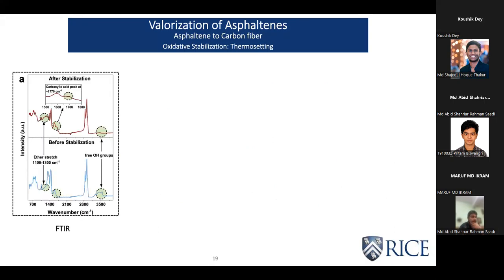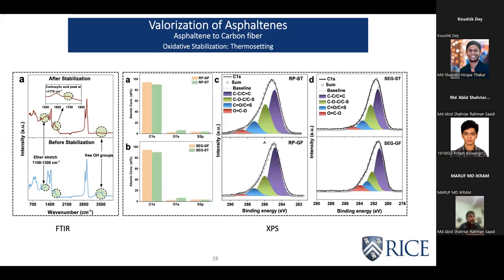We tried different types of stabilization routes, and the one that worked was the multi-step stabilization. We used FTIR, Fourier transform infrared spectroscopy, to confirm that the fibers had been oxidized. Here, before stabilization, and after stabilization, we saw this ether stretch. Again, here we saw an additional peak that corresponds to the carboxylic acid peak, which appears when you oxidize these fibers. Also, these OH groups diminish because after stabilization, the oxygen is involved in bond formation with carbon, so the OH group peak is diminished. We also did XPS. We saw that after stabilization, the carbon percentage decreased and the oxygen percentage increased, which again gave us proof that our fibers have been oxidized properly.